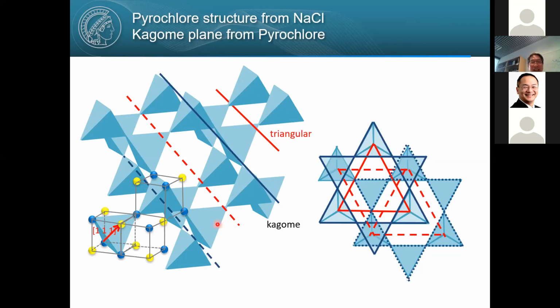Besides this pyrochlore structure, if you look very carefully along a 111 direction, you have a pile-up of this layer and this layer. This broken-line layer is triangular, and this blue layer is a Kagome layer. So the pyrochlore structure is a stack of triangular layers and Kagome layers.